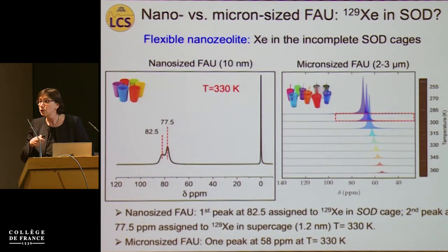Very recently, we were also surprised that these nanoparticles are flexible. They allow xenon to go not only in the supercages, but also in the open sodalite cages, which are located at the external surface of zeolite nanoparticles. And this is one example of how, by decreasing the size of the crystals, we could bring new properties to well-known materials. In this case, the nano-size faujasite with 10 nanometer size was compared with the classical micron-size faujasite.